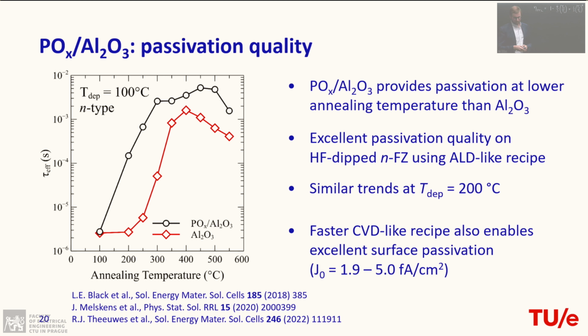And then also with the CVD-like recipes, we got very low J0 values, which is a recombination parameter, also linked to passivation, and you want to reach really low values for this.